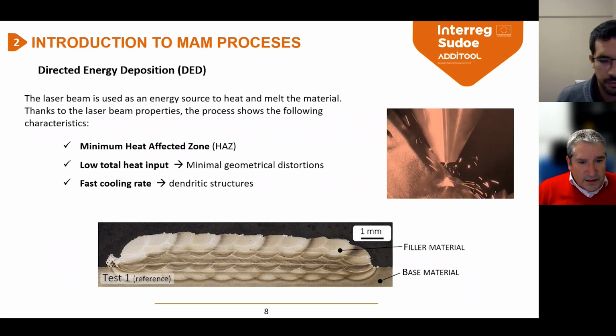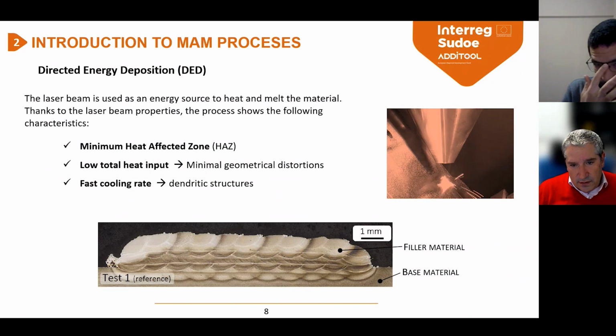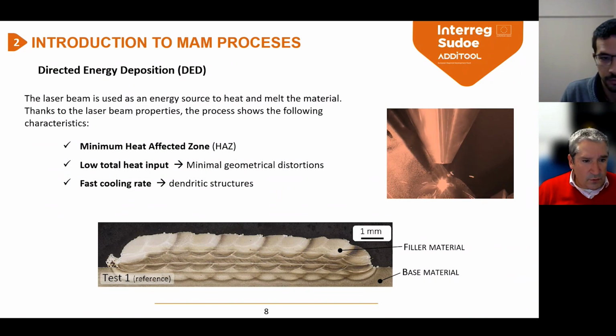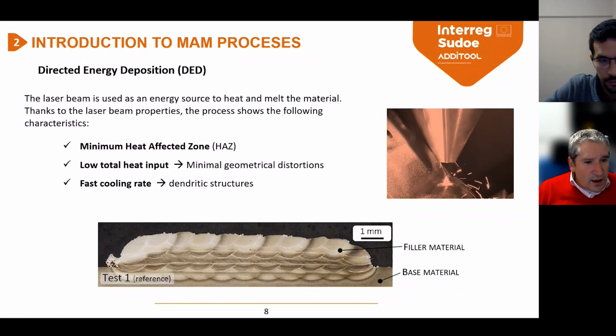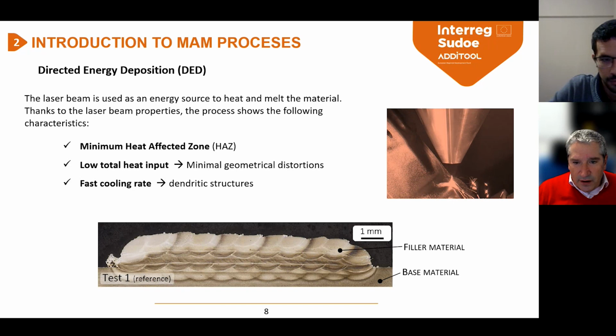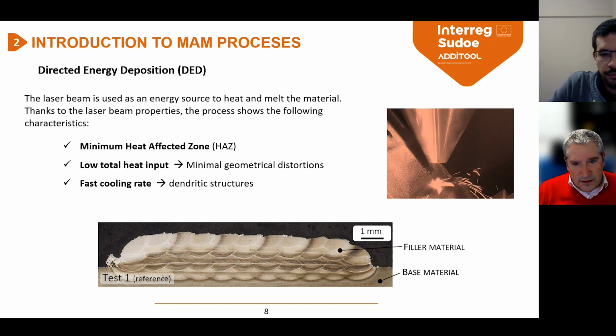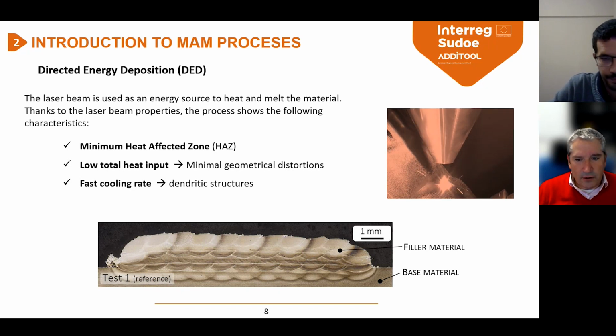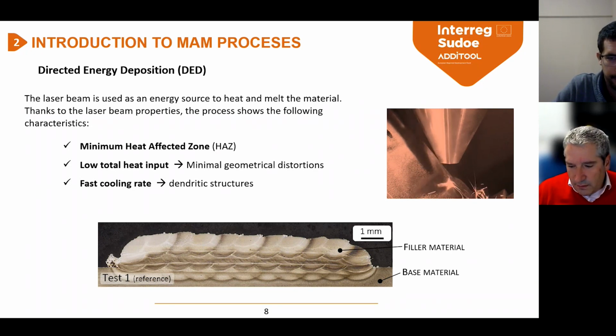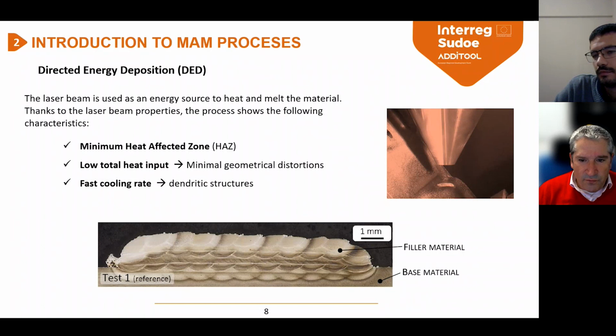Okay, in that case, the laser gives us very good quality in terms of a very minimum, very small heat affected zone, and we can melt a very local area. So in that case, we have a very good resolution. And also, if the process goes with the correct conditions, with the good parameters, we can obtain a fully dense and very good quality deposition of the material.